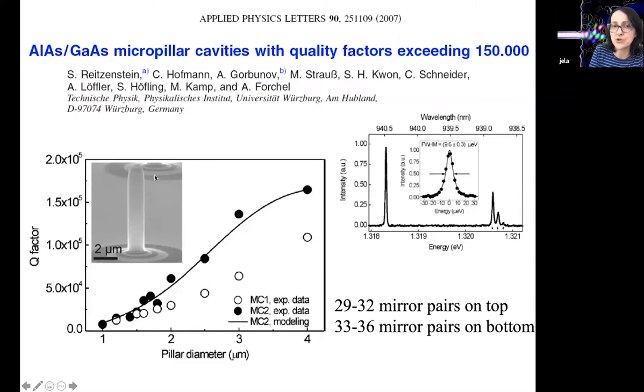As you're etching the structure, it starts to heat up because this is a very long etch, and that affects the etch profile. You see some undercut on some of the pillars that I showed you before. Also, there is a mask degradation for all the masks that you can deposit. You have to go to multi-layer masks, and even in this particular case, there is mask erosion eventually because you're running out of mask as you continue your etch. So it's not a trivial problem, especially to make high Q small volume resonators. But if you are okay with a moderate Q and decent volume, then you can actually make really good single photon sources in the weak coupling regime.